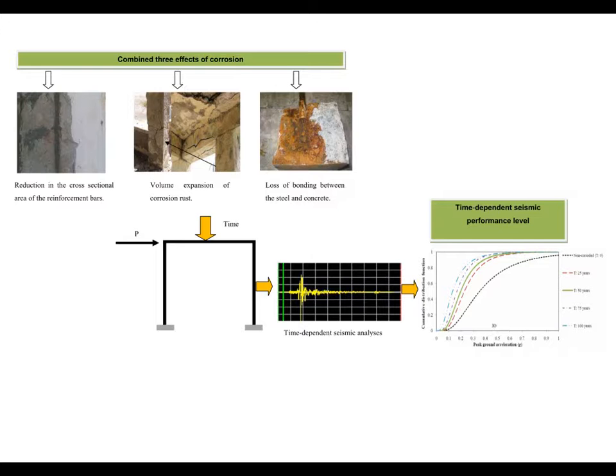For doing this, three combined corrosion parameters — which were loss of the cross-section area of reinforcement bars, reduction of the concrete strength, and additional displacement due to slip as a consequence of corrosion effects — were calculated as a function of the corrosion rate for five different time periods. Obtained results from corrosion analysis were then used to perform nonlinear time history analysis for 20 ground motion records.